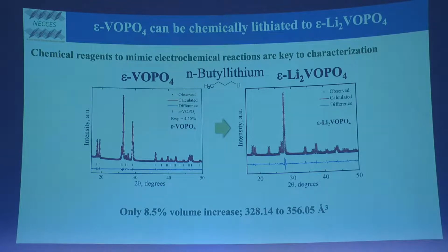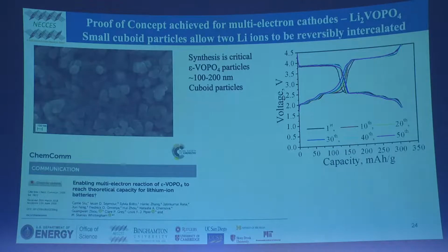So this is what we measured by synchrotron studies. We could actually get lattice parameters out. And this was a huge plus because we found that it expanded by, say there, about 8%, less than graphite when you put 2 lithiums in. If it only expands that much, it should be stable. So we measured both these structures. There are similar reagents you can use if you make a lithiated compound to take the lithium out.